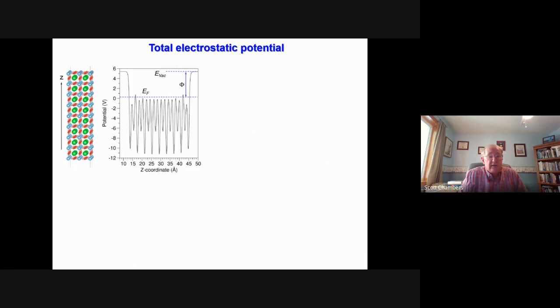Okay, last effect before we get to some examples is total electrostatic potential, another initial state effect. If you take any solid that you like and think about what the electric potential looks like as a function of distance through that solid, this is what you would get. And this happens to be for strontium titanate again. So this is a quantum mechanical cluster, and these are DFT calculations that my colleague Peter Shushko did here at PNNL. And this is the potential as a function of z coordinate through the material.